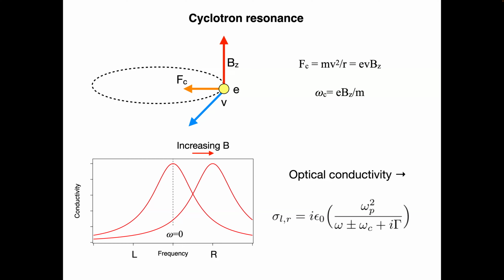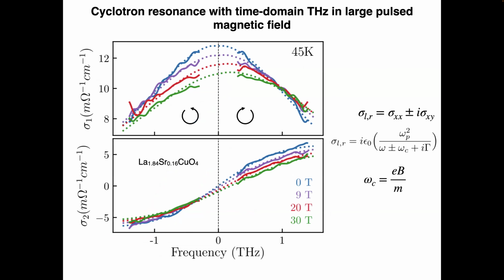Okay, and so we've done that. We're doing this in a lot of different contexts, but this is data which came through a collaboration with Scott Crooker and his group in Los Alamos, where they built a system to do terahertz spectroscopy out to really high magnetic fields. So even in some cases, we go higher than 30 Tesla. This is lanthanum strontium copper oxide, near optimal doping. The blue curves here are the zero field data, and then we apply a field to it, and you can see how this maximum shifts.